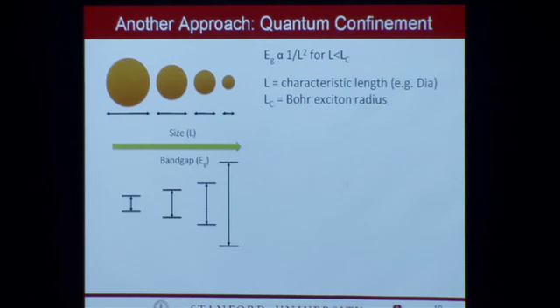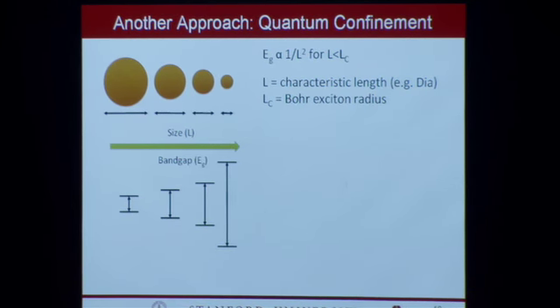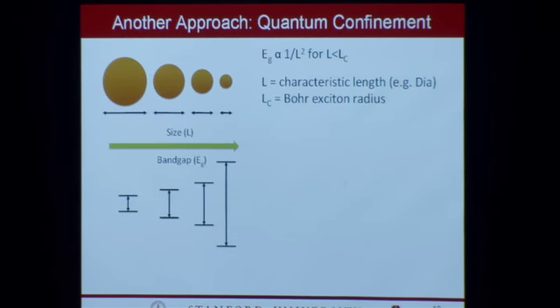So we're going to go the different direction. Instead of taking, say, TiO2 or zinc oxide, which are wide bandgap semiconductors, and mixing in some other elements to alloy it and make for a smaller bandgap and increase the light absorption, we're going to start with something that has a bandgap that is too small to begin with, but as we shrink the size of that semiconductor, we expect that we can widen the bandgap to hopefully hit the target of 1.8 to 2.0 eV that I described before.